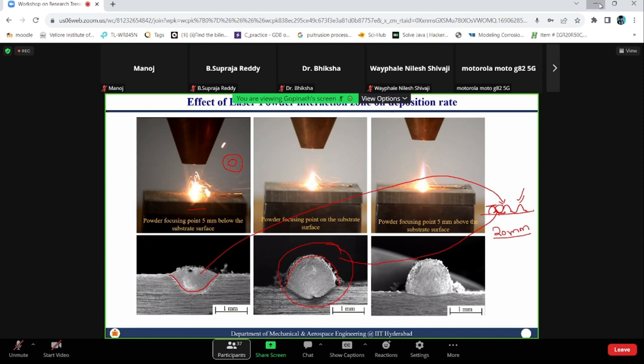Now, what is this extreme high speed laser cladding? What we are trying to do here is allow the laser and powder to interact more, which means we are going to a higher standoff distance, like 25 mm, so that most of the energy is absorbed by the powder. Also, typically, I have used 600 watt for deposition, cladding or additive manufacturing. Instead of that, now I will use 2 kilowatt, or 2000 watt.